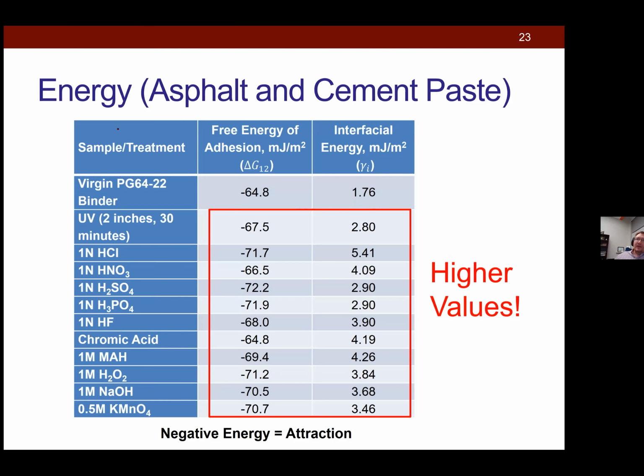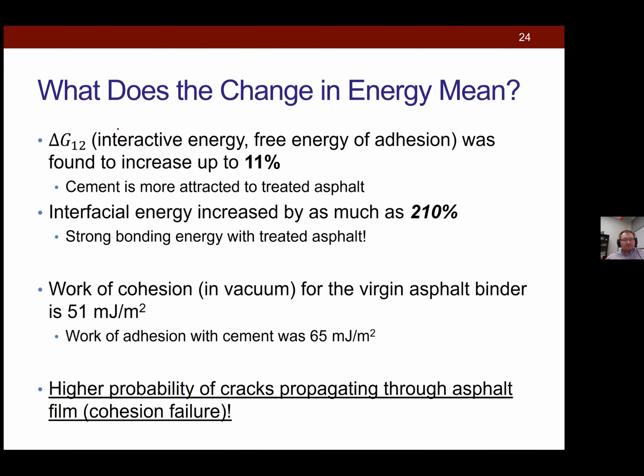And again, I kind of had to skip over a lot of information here, but we found that we could change the interfacial energy between asphalt and cement paste by doing some oxidation to the asphalt. All right, so we were able to find that we could make some modifications and actually increase the energy of adhesion. Okay, but the problem was we still had that larger, more porous ITZ. The other problem that's kind of fascinating is that the work of cohesion of the asphalt, all right, so the energy it takes to split the asphalt apart was still less than the amount of energy to split cement from asphalt. Okay, so the energy of adhesion was stronger than cohesion.